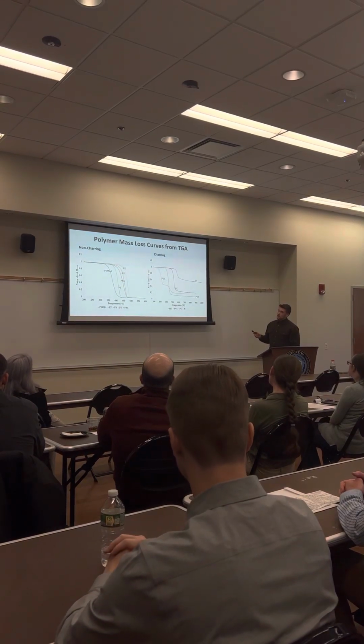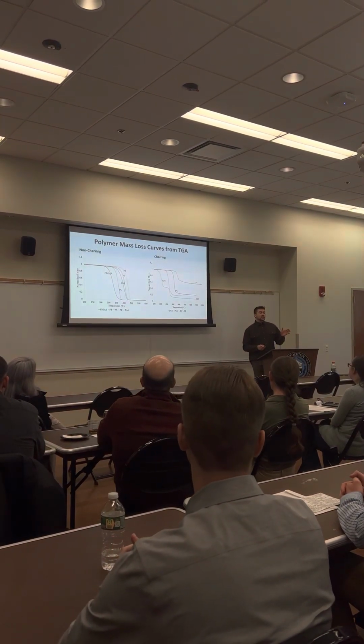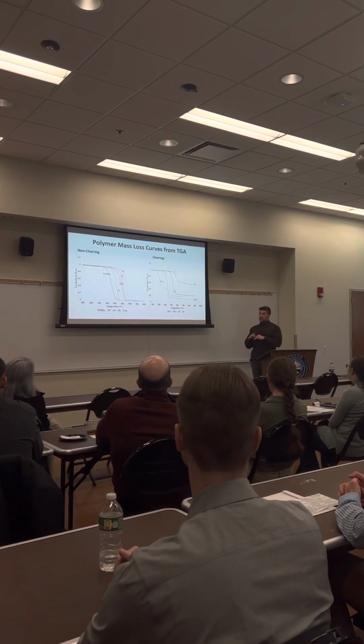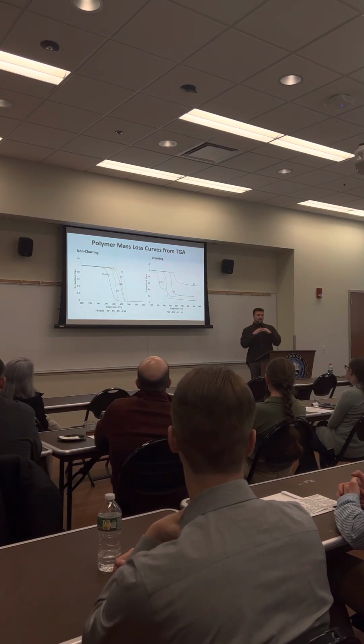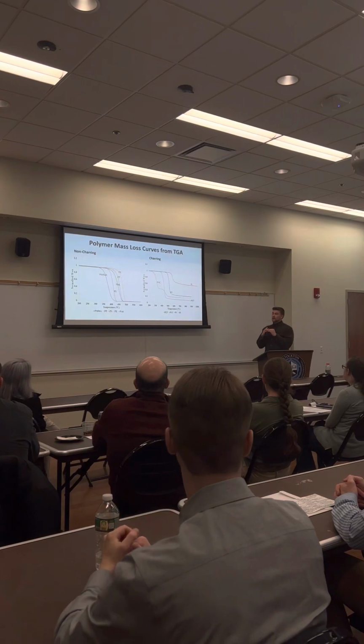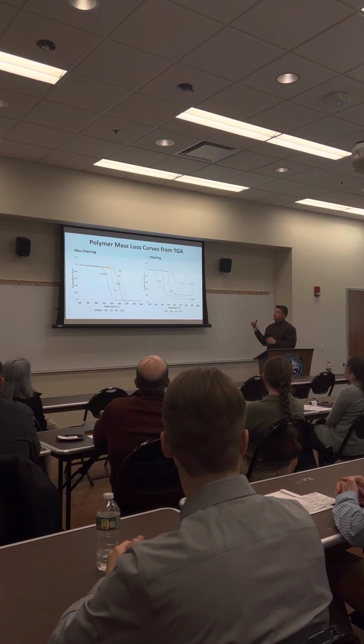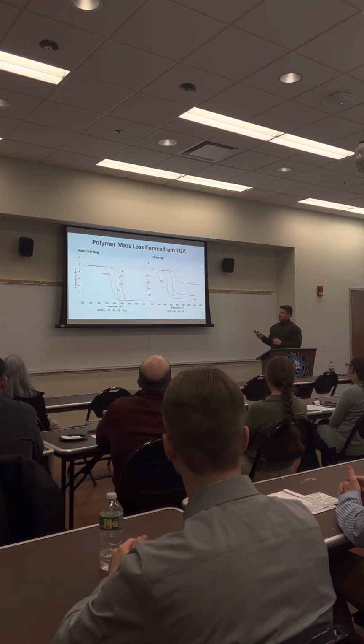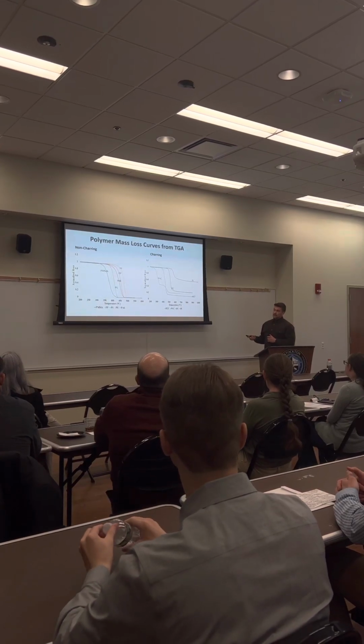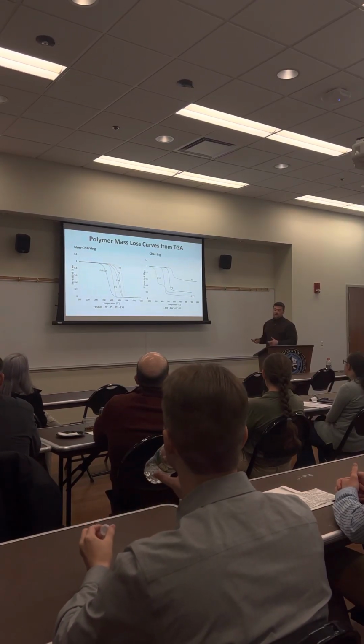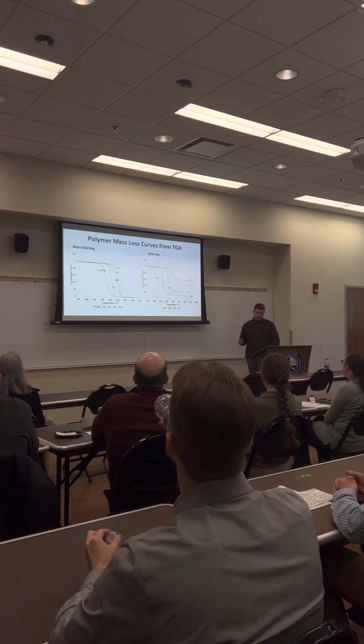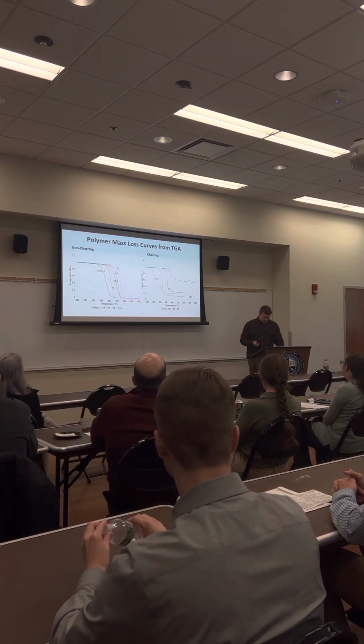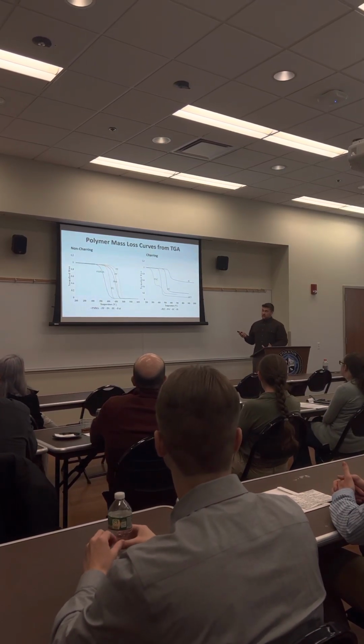These polymers are called charring polymers because once they reach a certain temperature, they start to produce a kind of carbonaceous residue around themselves to where they will not continue to further degrade. So that's why they stop at the heating rates that we ran them at and not all the way at 0, because there's still residue or mass left over from the sample. The non-charring species do not leave residue.